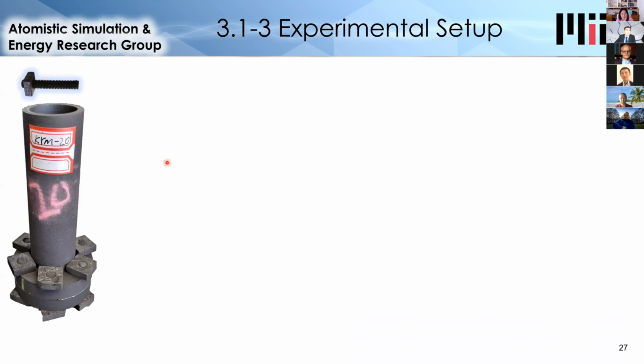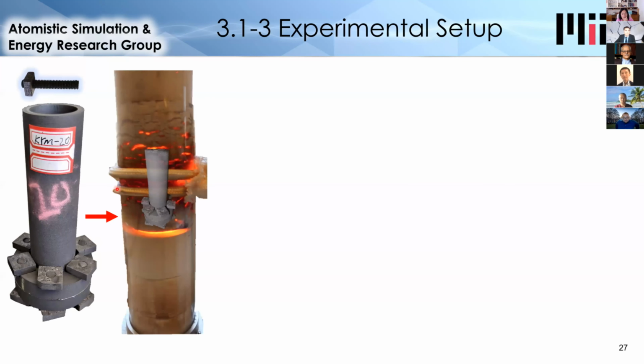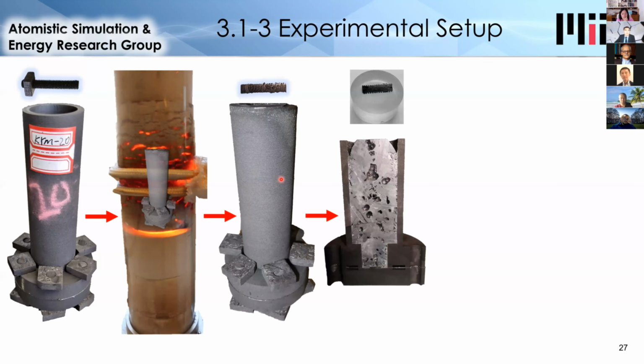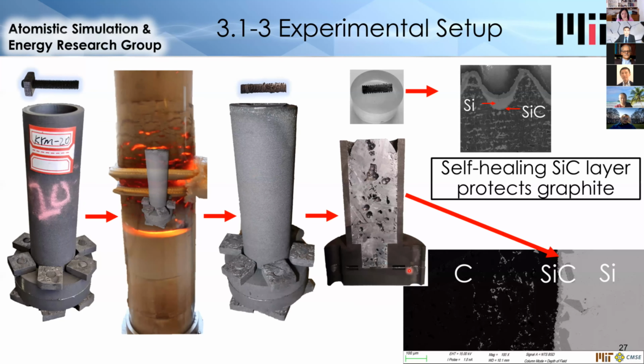So the way these experiments were conducted, I started with a tank that was about 4 inches tall. It's made from 2 pieces and sealed together, not out of necessity, but to demonstrate the ability to seal. And these tanks were bolted together with these carbon fiber bolts shown here. The system was heated, usually to around 2200 degrees Celsius for several hours, and then removed from the system, cross-sectioned, and looked at with a scanning electron microscope to see what happens at the interface between the silicon and the